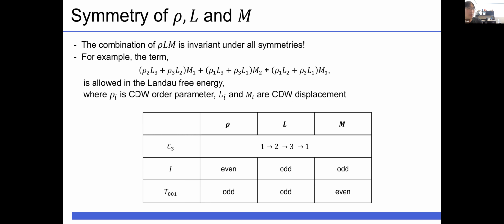The combination of rho, L, and M can be included in the Landau free energy if it is invariant under the symmetry operations. And this term can be an example. The threefold rotation permutes indices 1, 2, 3, 1, and this permutation does not change the term. And for the inversion operator, rho becomes even and L and M become odd. So the product of three becomes even. So this term is invariant under the inversion symmetry. It is also invariant under other symmetry operations.